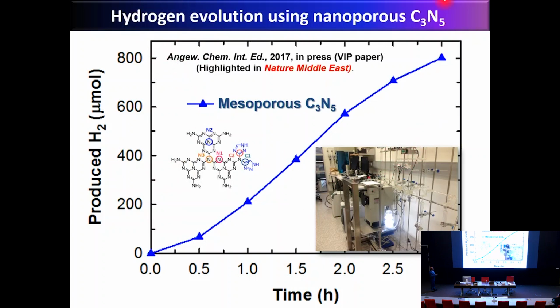The high performance is mainly due to the fact that you have less electron-hole recombination, and a huge absorption of visible light. But still, it is not enough, right? Because it increased from only 300 to only 800 after 3 hours of the reaction under visible light photocatalysis. So can we increase the performance of this material? Now the band gap is 2.2, decreased from 2.7 to 2.2.